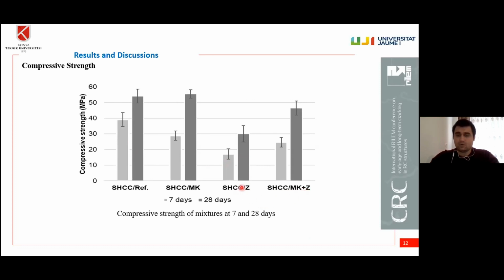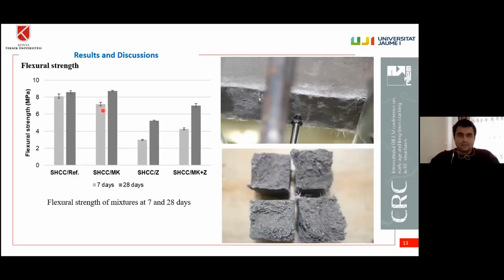For the zeolite bearing specimens, both in single and binary form, we can see the slow pace of pozzolanic reaction of zeolite, so these specimens were lower than the reference specimens in terms of compressive strength. For the flexural strength, a similar trend is also valid. In some literature studies, it is reported that zeolite can actively react with the matrix for up to 2 or 3 years. So considering the curing ages, these are really early ages, and we can see the slow pace of pozzolanic reaction of zeolite.